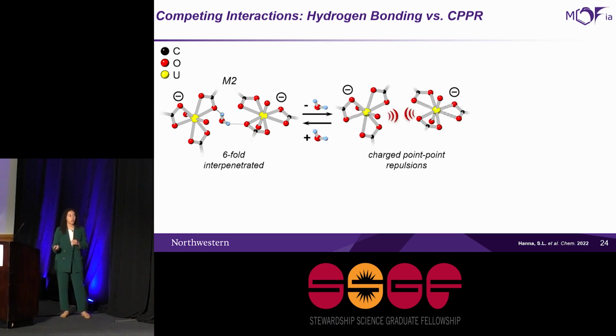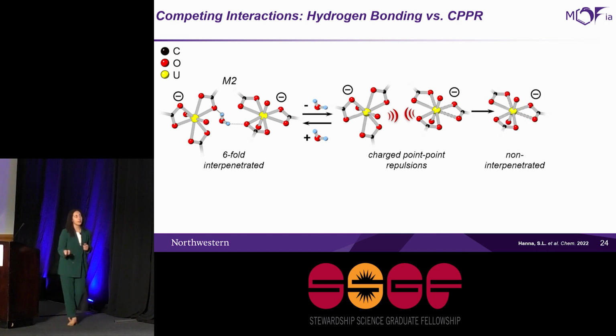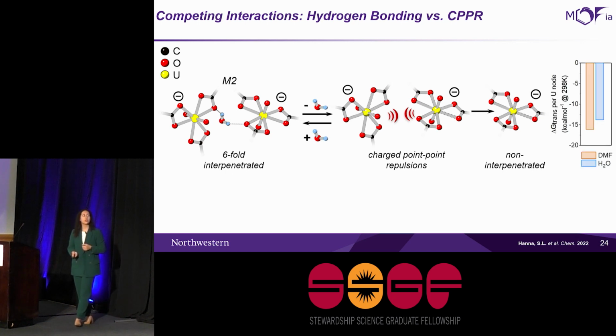However, we know that these charged point-point repulsions are also happening, and so you can deduce from this that there are these two competing interactions, one that holds the 6 networks together and one that forces them apart from each other. And so at the end of the day, we see that this non-interpenetrated structure results and these charged point-point repulsions win. You can also calculate this looking at the free energy of this transformation in the presence of water, which is kind of fallen off of here, but it's the blue trace you can see is less favorable than the red trace here.